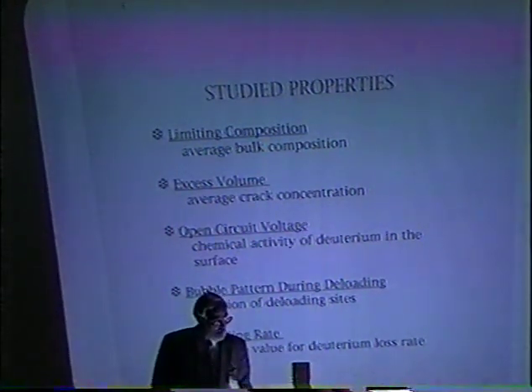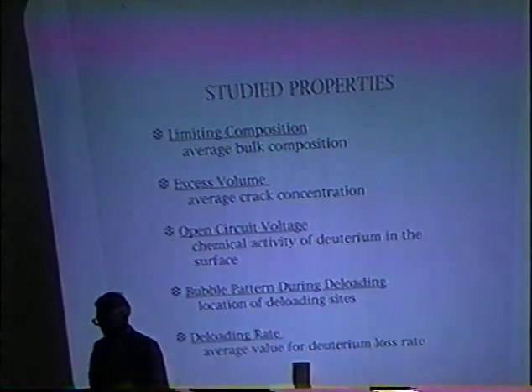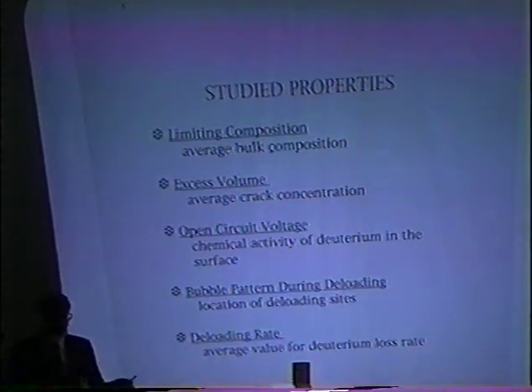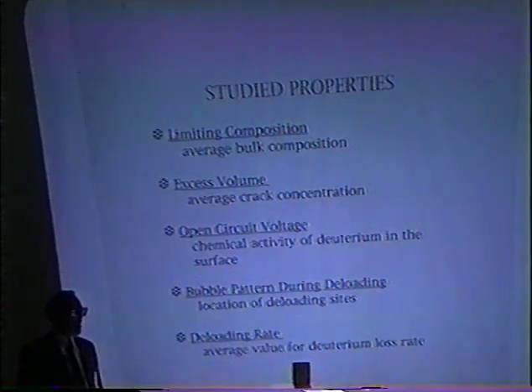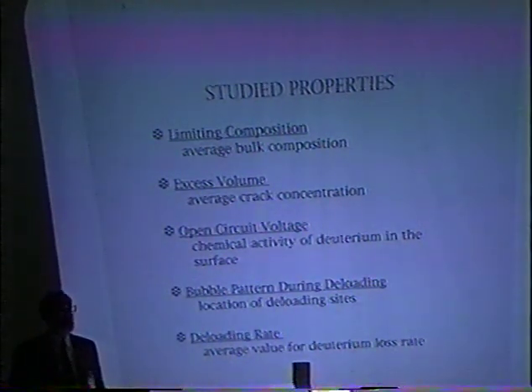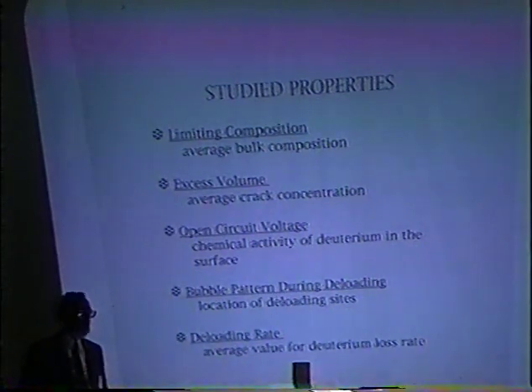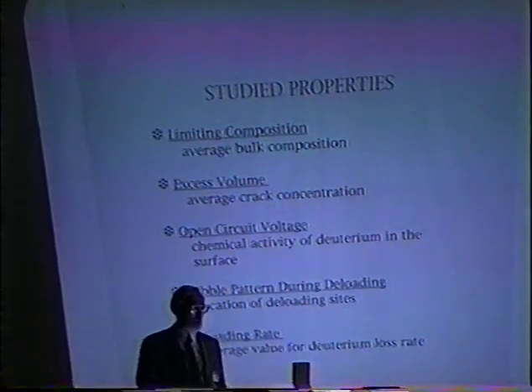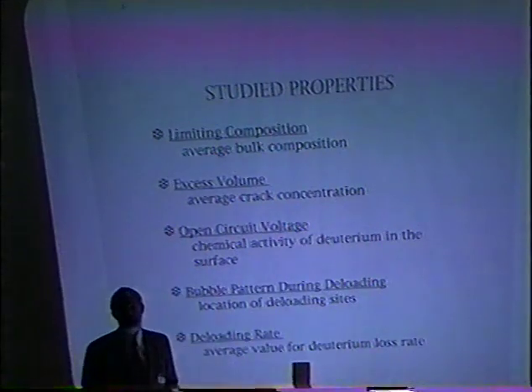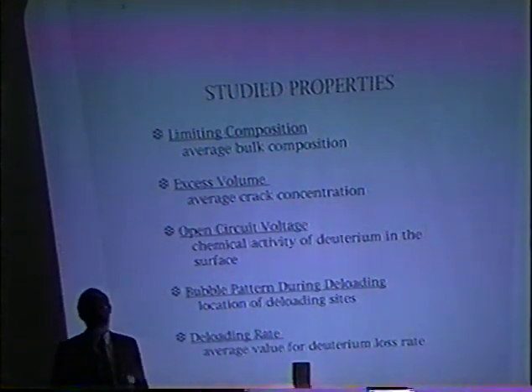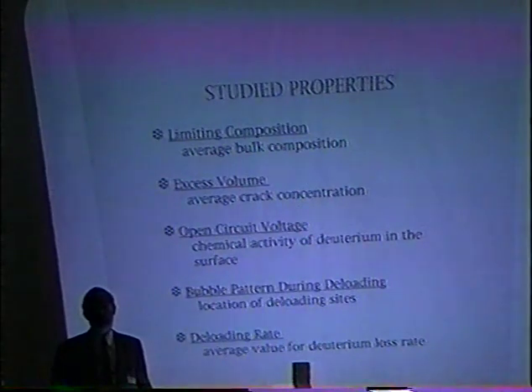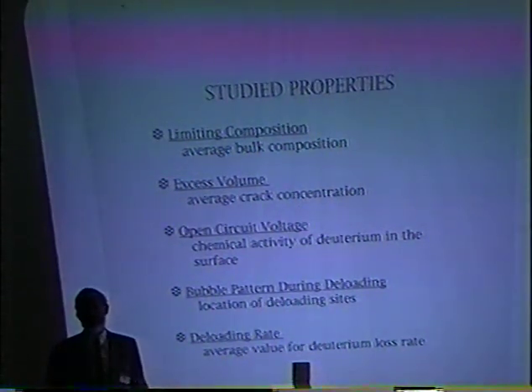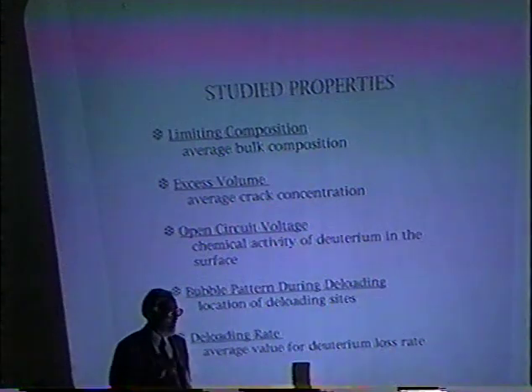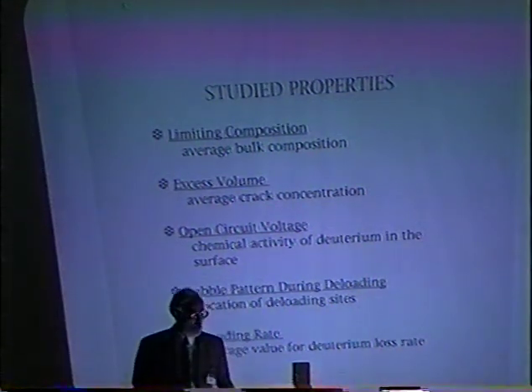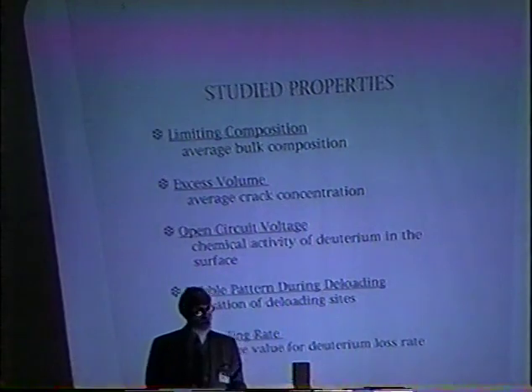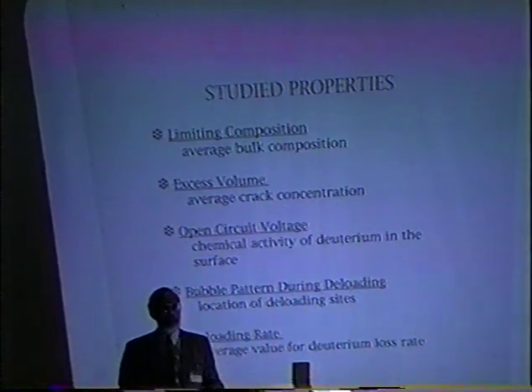The deloading rate is determined by taking the sample out of the cell, turning off the current, starting a clock, and measuring the composition as a function of time. If you plot D over Pd ratio as a function of the square root of time, most of the time you get a straight line. And in palladium you have to say most of the time because there's always an exception. But you get a straight line, and the slope of that line gives you a measure of how effectively the hydrogen is leaving the sample.